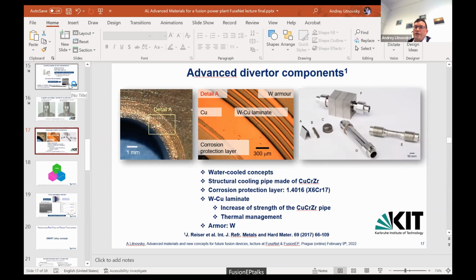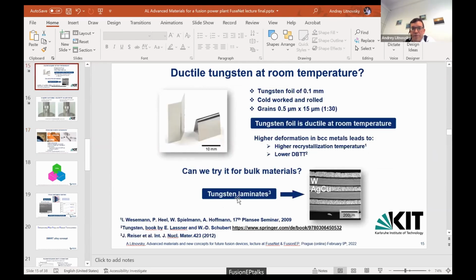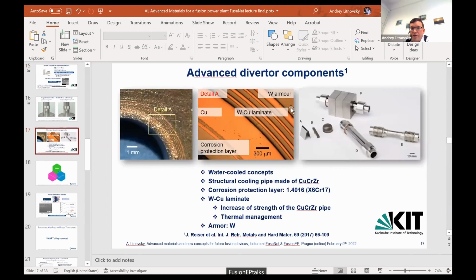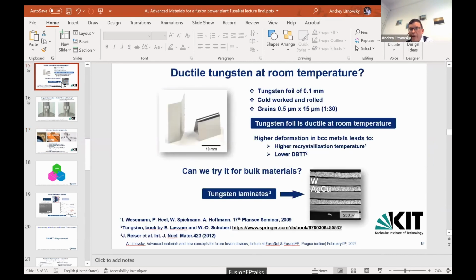Yes, the answer will be, you're absolutely right. The silver is not allowed for the fusion purposes. This was the first try and error method, which our colleagues used to see if this concept works at all, to see if there are no cracks and so on. If you can go here, there is no silver anymore. So this is basically like a layered, functionally graded material. So we can play with the thickness a little bit. We can play with the amount of the layers in order to accommodate different coefficients. But the silver was used only for the first time to see if the technology works, if we can at all make such laminates. It is, strictly speaking, not fusion relevant. Thank you very much. It's very interesting.